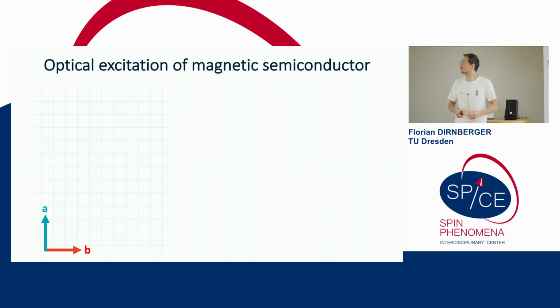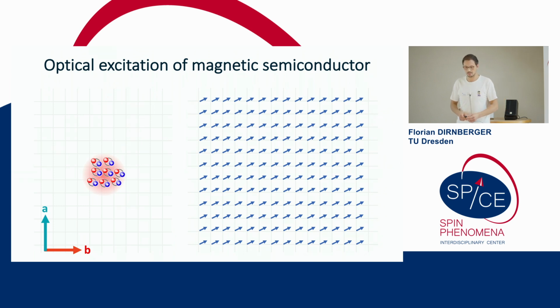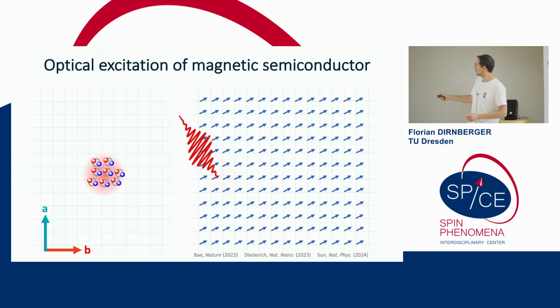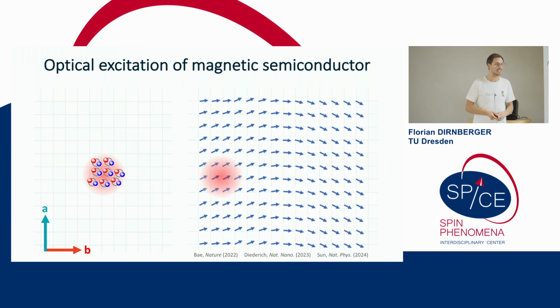So in order to motivate this model that we have developed, I'd like to briefly consider what it means when we shine an ultrafast laser pulse on a magnetic semiconductor like chromium sulfide bromide. We, of course, know that we shine this non-resonant laser pulse to create the density of excitons. That is very clear because we see the light that comes out from these excitons, so we know our excitation works. We do also know from a lot of previous work on other magnetic materials, or more specifically from these works, that optical excitation with very similar conditions that we use in our experiment creates an excitation of the magnetic order. So people have used that to study the transport of excitons in this material. If you imagine that in this simulation here, after a certain time there's a magnon wave that is propagating away from the excitation region, and that happens both along the A and along the B direction of the crystal.